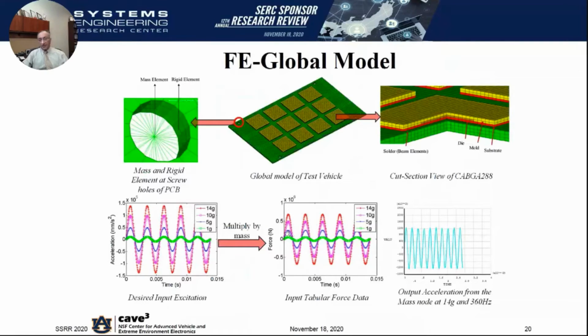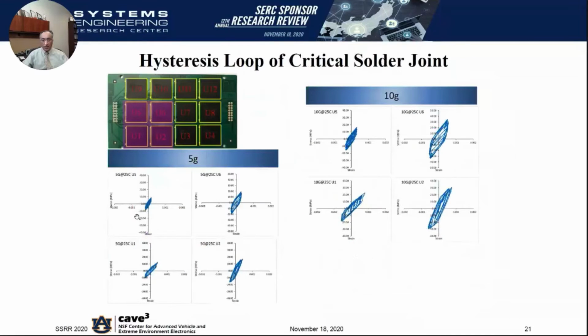So what we have then done is we have simulated, so that was experimental data. We have simulated the board assembly with the various package elements. So you can actually see the electronic molding compound, the chip, you can see the substrate, you can see the various interconnects. These are solder joints that have been modeled as Timoshenko beam elements in the global model. And then we've done a local model with the brick elements as well. So then we impose a high G load on the model. And then we actually extract what's called the hysteresis loop. So larger values of the hysteresis loop correspond to a higher amount of plastic work.